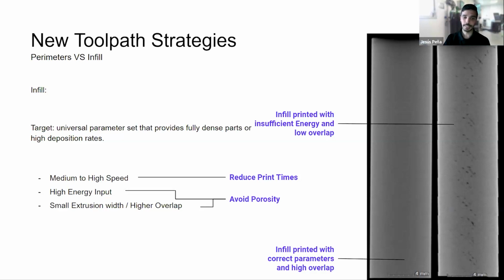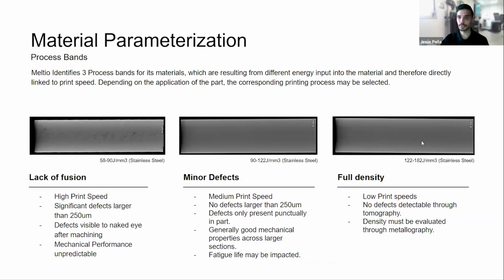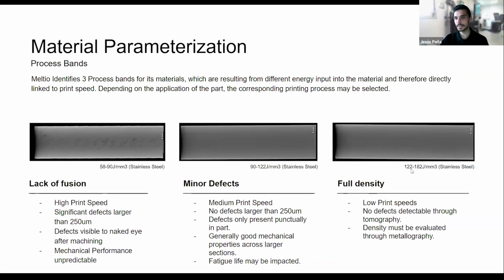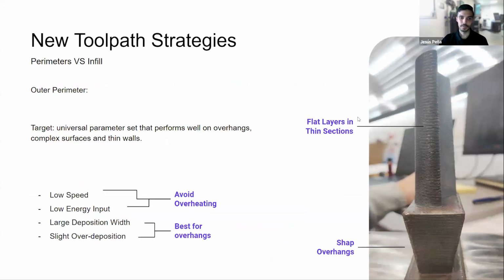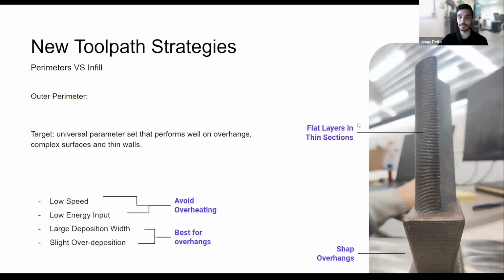So it depends on the actual diameter of the hot wire I use, and also because the hot wire at the end adds energy to the equation, an amount of wattage together with laser power. Let's say that I want to avoid porosity completely in my part. I should always focus on the band that I mentioned before, the fully dense band, that in this case for stainless steel starts at 122 joules per cubic millimeter. And of course, we have developed the technology for a while already. We have already seen what the variables are that affect the process. We always focus with our toolpath strategies, with our software, with Horizon, with Space, on having those fully dense parameters, also in case there is any other application for minor defects.